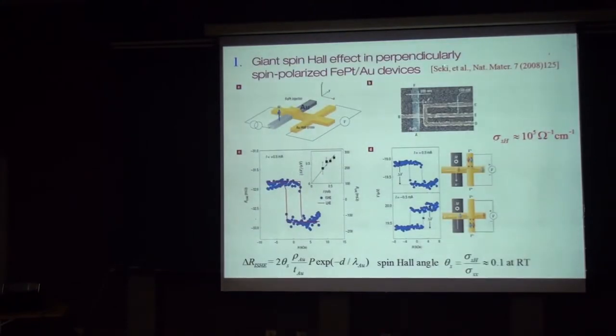And this is the paper published by Seki I mentioned before. When they measured spin Hall effect in gold Hall bar, and accidentally they found that the spin Hall effect can be 100,000 or more. This is really gigantic. Two-order magnitude larger than the spin Hall effect I mentioned before in platinum.